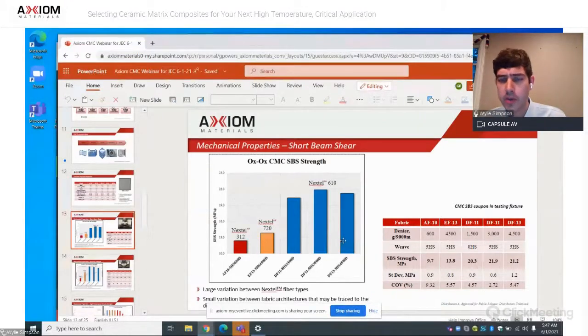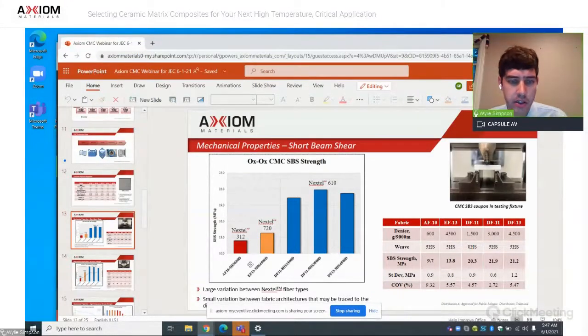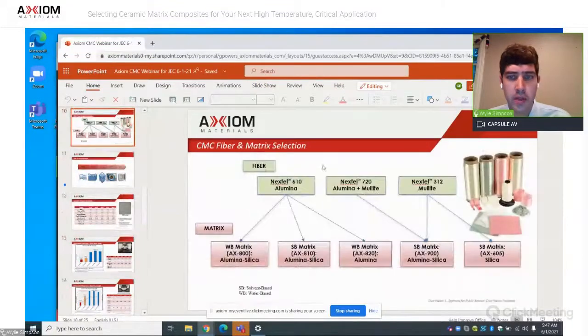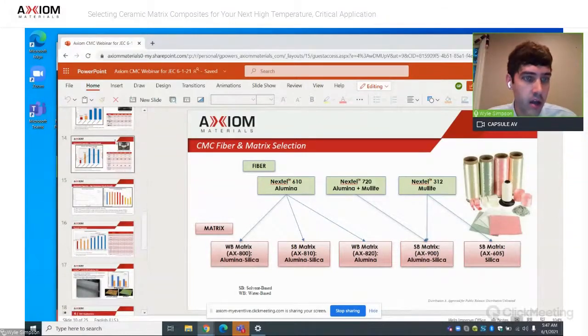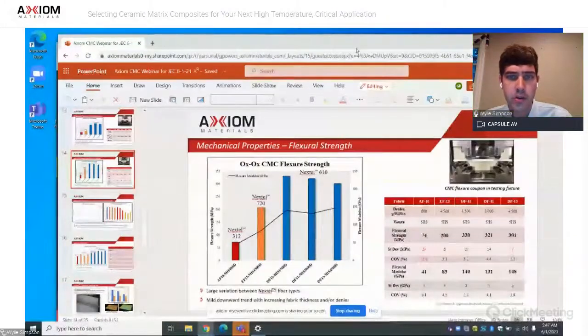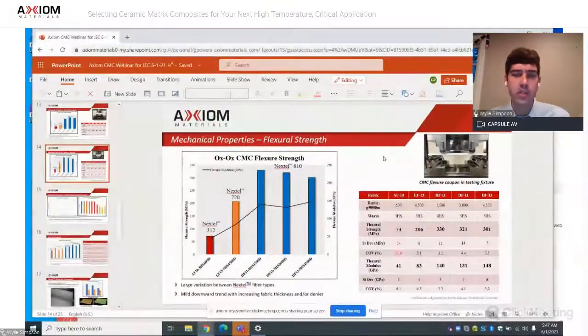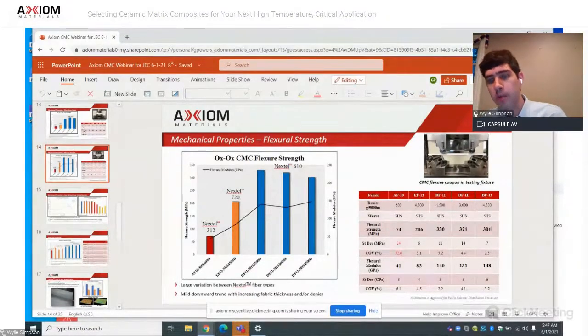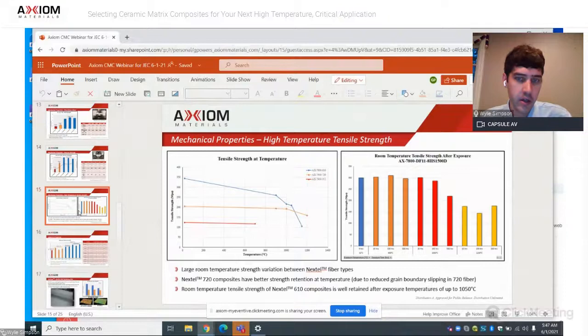So you can see some of the short beam shear properties and the stark difference between the Nextel fiber types. I may have talked a little bit quickly through that, but there are those three different Nextel fibers: the 610, which is all alumina, the 720 alumina mullite, and the 312, which is more the mullite brand. So here you can see the short beam shear strength as well as the flex strength, a bunch of stark differences between the fiber systems, where the peak flexural strength is around 330 megapascals, and the 312 has more around that 74 megapascals.